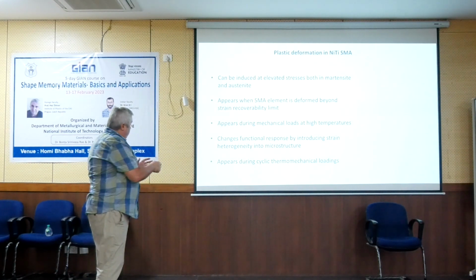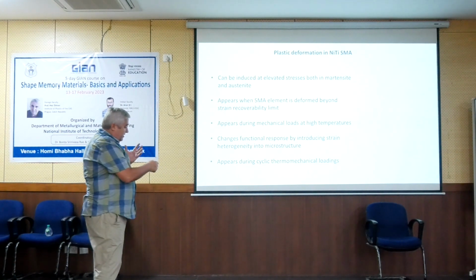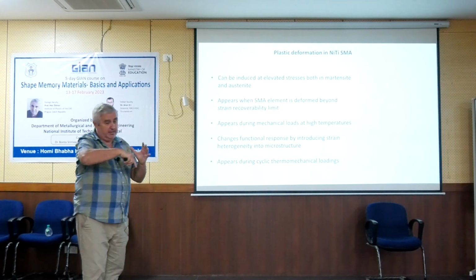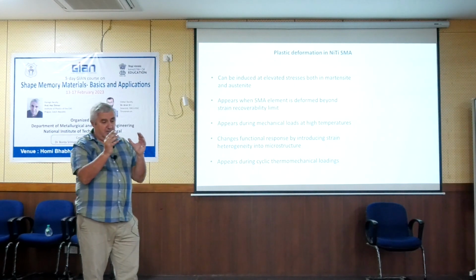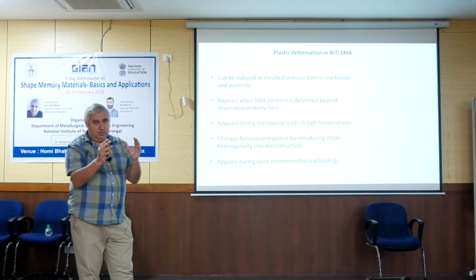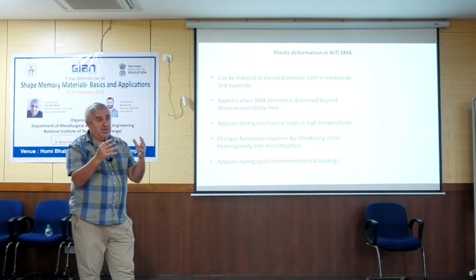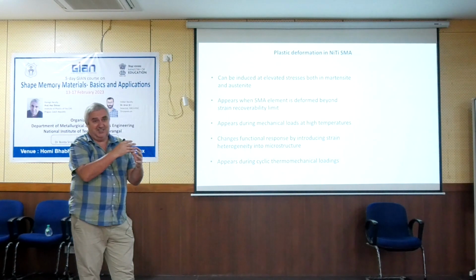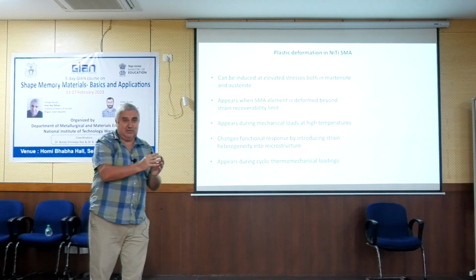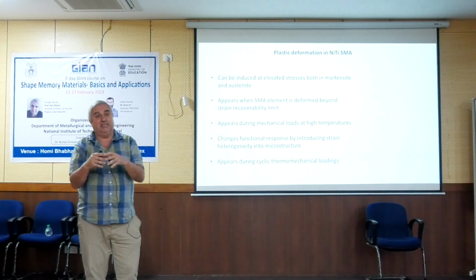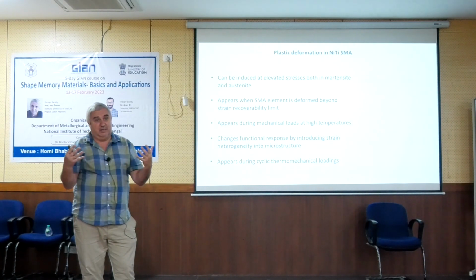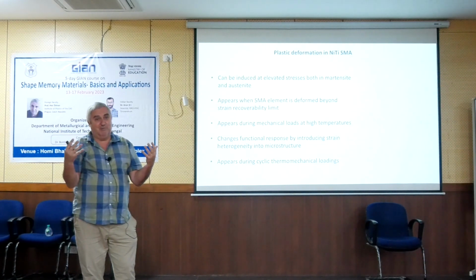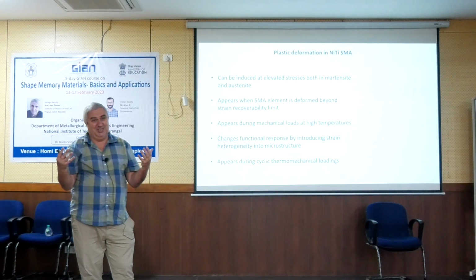But if I have simultaneous plasticity and make closed-loop cycles, there will be unrecovered strain, so some plastic strain will remain, but also the sample will change because you will have these dislocations inside. And the sample without dislocations and with dislocations is a different sample. So now I need a model for a different sample because my material parameters are changing.